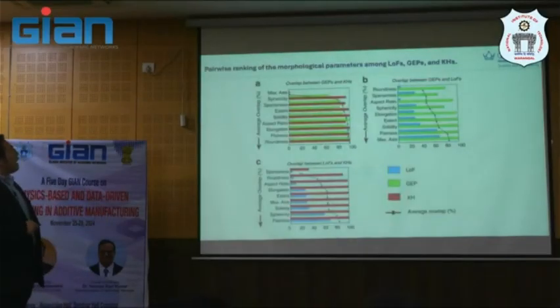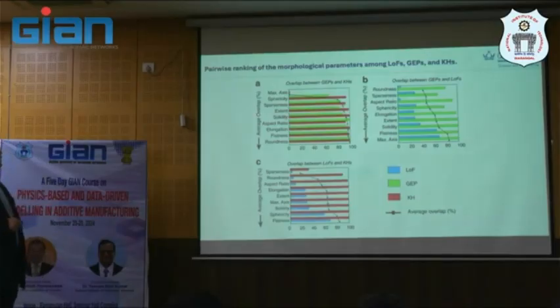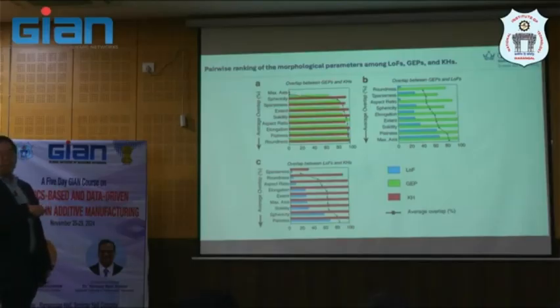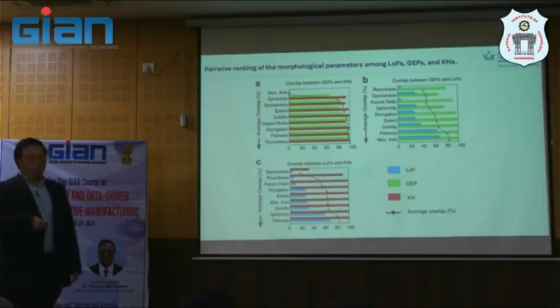And then what they do later is rank the morphology parameters to understand the extent of the overlap between them: sphericity, which is about the shape factor, sparseness, extent, solidity, aspect ratio, elongation. These are the geometry factors that they are looking at, basically talking about the porosity only. What is the overlap between gas entrapment porosity and keyhole, gas entrapment and lack of fusion, lack of fusion and keyhole? There will be some overlapping, but they try to rank in a pairwise manner to understand the overlapping percentage between each pair of porosity types. I think this is a good and quite clever statistical approach that they use to extract statistics for this titanium 6-4 process.